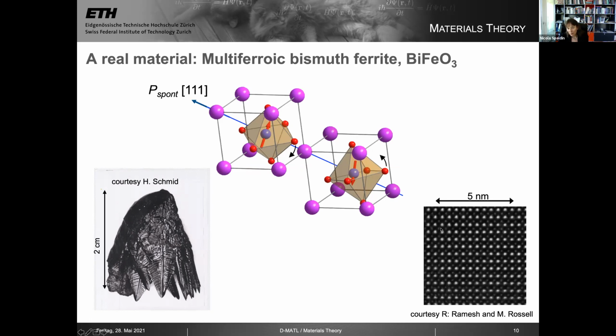And maybe you can see, if you have a good screen, these very slightly lighter dots in the middle. These are the iron ions. One doesn't see the oxygens with this technique. And if you have very good eyesight, you'll see that the iron ions are not exactly in the middle of the bismuth ions. And that's because there's a structural distortion in the material that makes the dipole moment. Of course, it would be easier to see the dipole if we saw also the oxygen anions. So this was a real breakthrough for the field of understanding ferroelectricity and these magnetic ferroelectrics when such beautiful high quality films could be made.